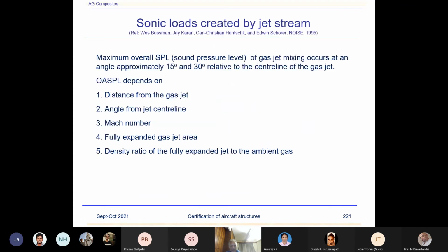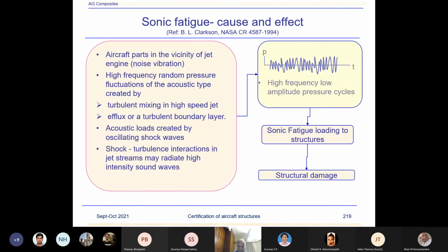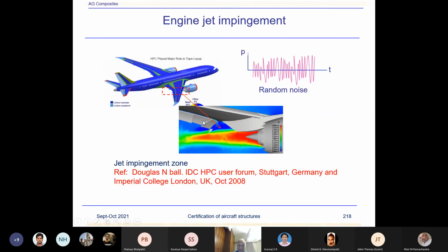So essentially, sonic fatigue, suppose we are dealing with this flaperon over here. Due to this, it creates vibrations. Now, these vibrations are low pressure, high cycle vibrations, essentially a fatigue loading. So you have to generate, using a sonic spectrum, the amount of loads being created. The pressure distribution in various zones is converted to the fatigue load, and that fatigue load is compared for the fatigue endurance limit using the stress fatigue diagram, stress cycle diagram.